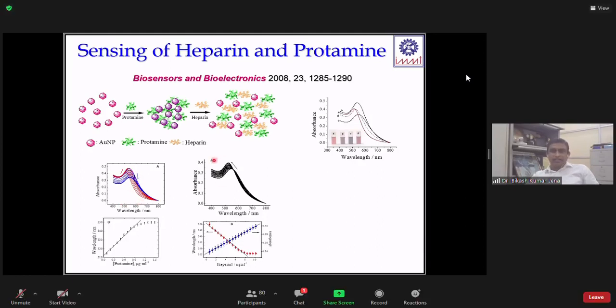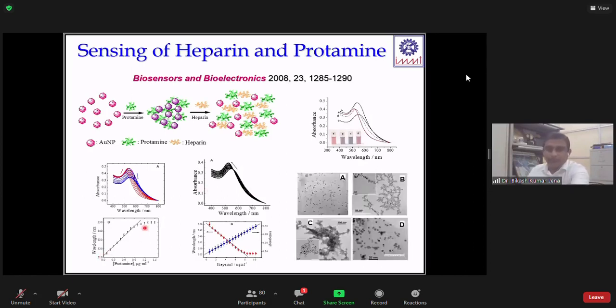And from this shift in the absorbance and also the shifting of wavelength, that can give you the change in the concentration of protamine. And when you add heparin, you can see it further releases, and it goes in this direction. It is releasing the nanoparticle, the absorbance is increasing.